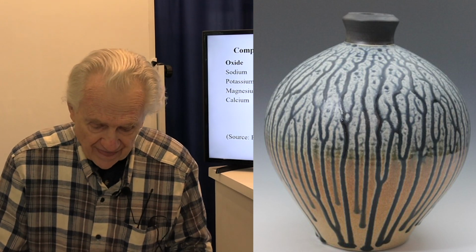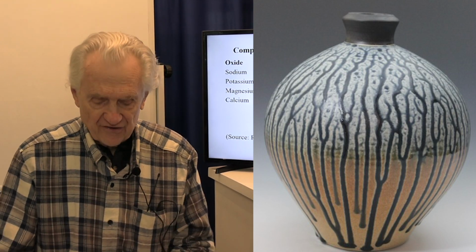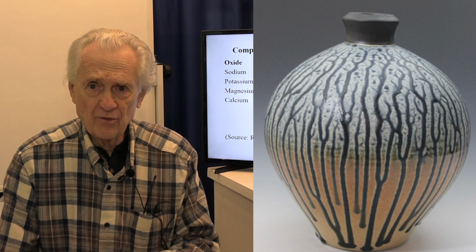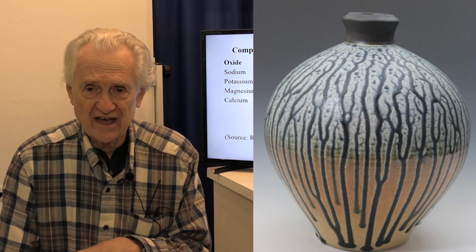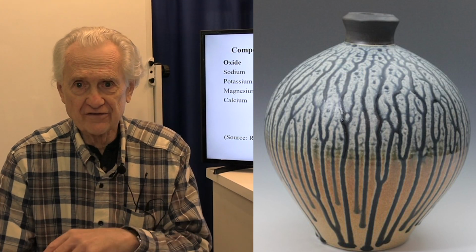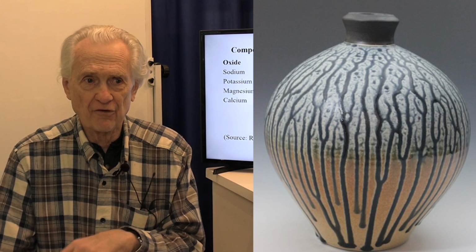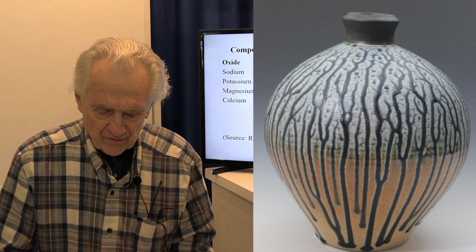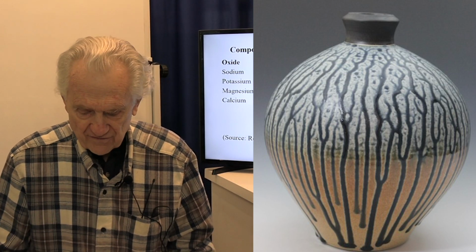It's very caustic. But anyway, you stir it in the water, let it sit overnight, and then I drain off the water, pour the water off. And by the way, be careful where you pour that water, because that is very caustic. That's lye. So don't go out and pour it under your favorite rhododendron tree, because you won't have a rhododendron tree anymore, okay? And then I usually recommend repeating the soaking and the pouring off of the water at least 2 more times,